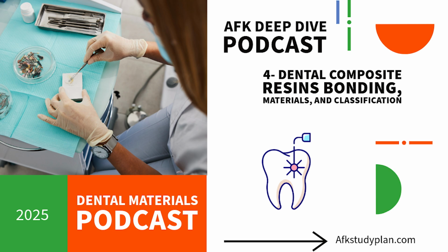Okay, this has been a fantastic deep dive. Let's try and quickly summarize the really key points. Sure. We saw the move from amalgam, driven by aesthetics and some clinical concerns. Then the core of it, bonding to tooth structure. That involves meticulous surface prep, the acid etch. Right, creating micro roughness. Exactly. Then the different needs for enamel, dry, versus dentin, moist. That critical priming step for dentin to manage moisture and allow bonding. Using those two-sided primer molecules? Yep. Followed by the adhesive resin itself, linking the tooth to the composite.